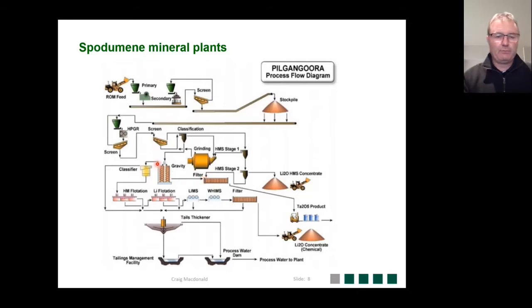The fine product from the milling circuit is passed through an upflow classifier to recover mica, and then the underflow is fed to spodumene mineral flotation. The concentrate from flotation is then passed through magnetic separation, and then the product is dewatered in a pressure filter to produce a cake, which is the fine spodumene concentrate. So that would be typical of a plant with both dense medium separation and flotation, and also a plant that would be recovering tantalite as a byproduct.